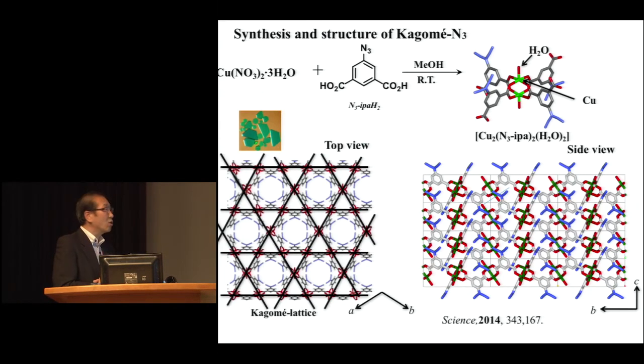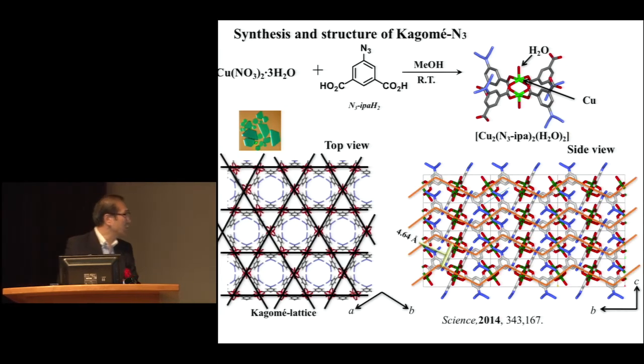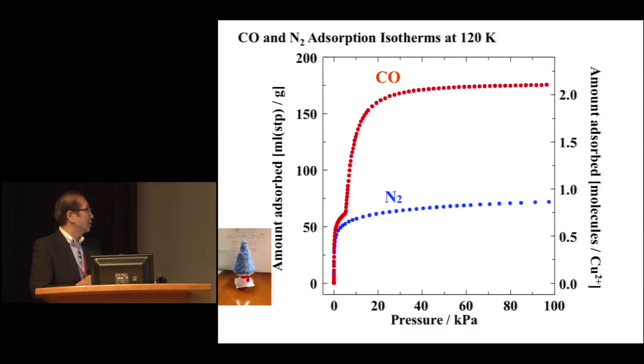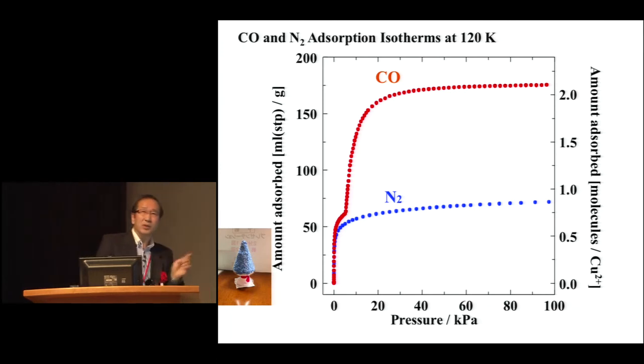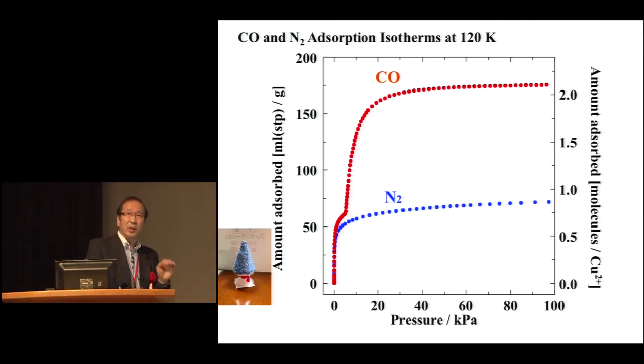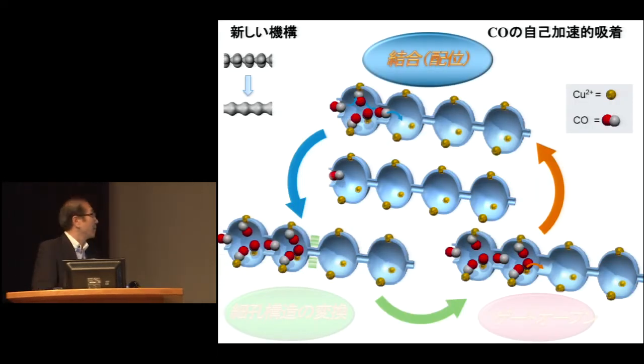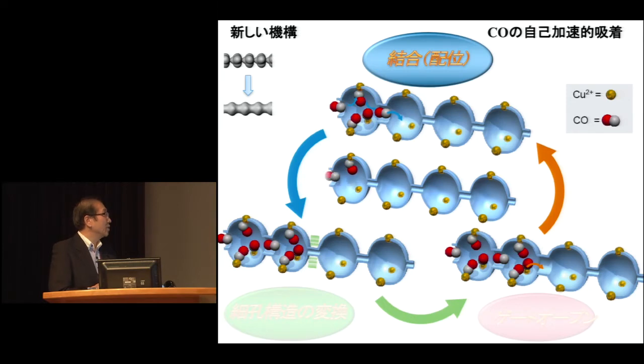And our material with Kagome structure, we wanted to separate these two different gases. And this comes as a very beautiful green crystal using the copper and the organic molecules. Then you can see that the N2 absorption stays low, but the absorption of CO dramatically increased with the pressure. Why is it? We analyzed the mechanism, and I will show you the essence of the mechanism with a movie.